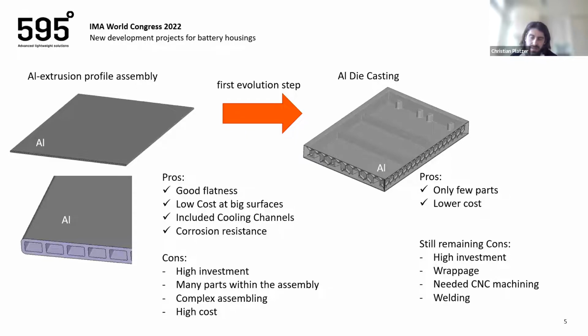So what we are seeing at our customers is that they somehow go away from these extrusion profiles and try to go into big castings, but aluminum castings. The advantage is that you only need a few parts. One part is not possible because we need to somehow create those cooling channels for the coolant, and they cannot be cast. But by having this single big shot, you can save lots of costs. But even in this evolution step, you have some still remaining drawbacks that we will also investigate in the next slide a little bit closer.